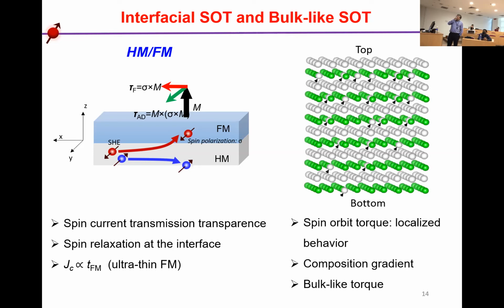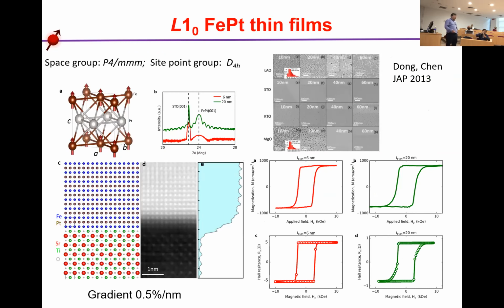So if we use this kind of bulk material, there's no interface. We suppose one atom layer of heavy metal atoms and one atom layer of magnetic atoms. Alternatively, we change their composition along this direction, so we can also break the inversion symmetry. Therefore, there is a net torque in these materials. This inversion symmetry is induced by the composition gradient. So we choose the L10 FePt thin films.